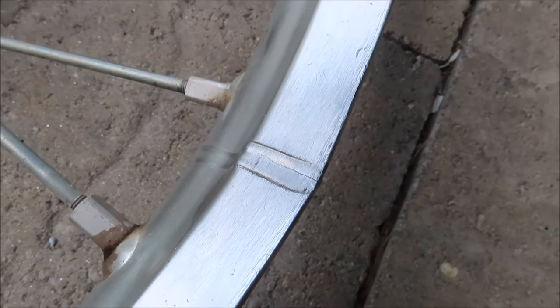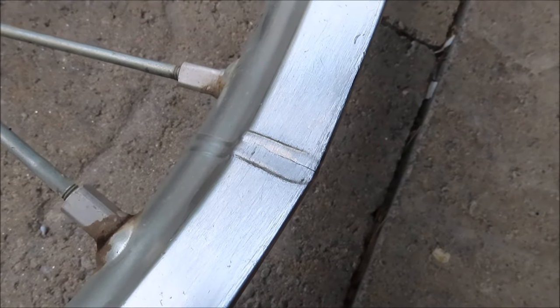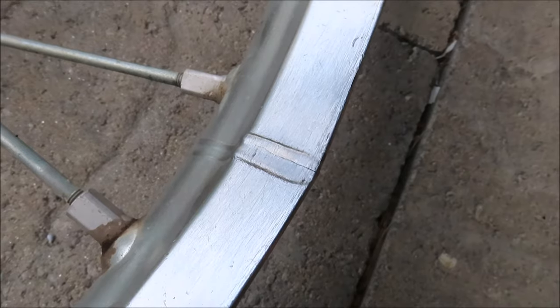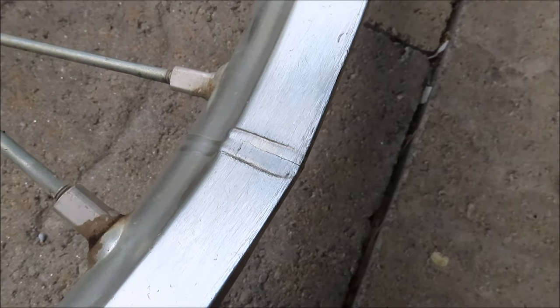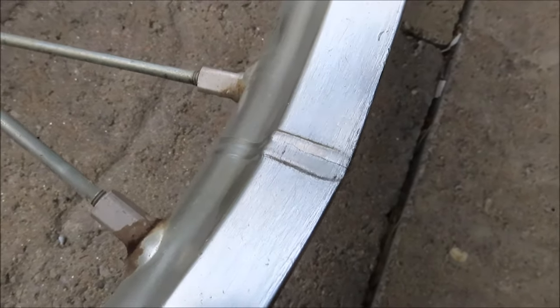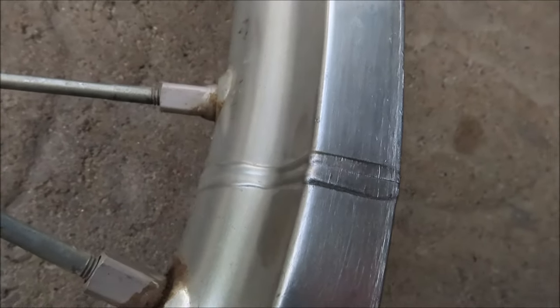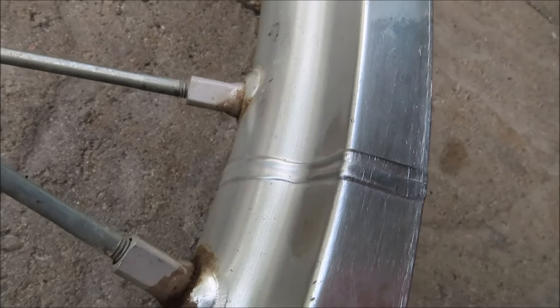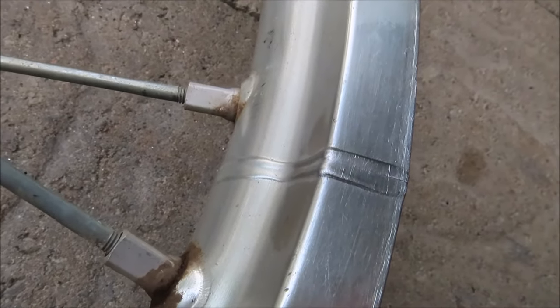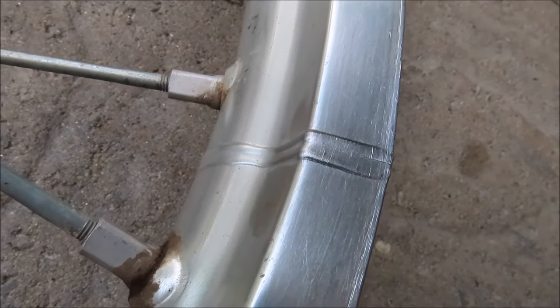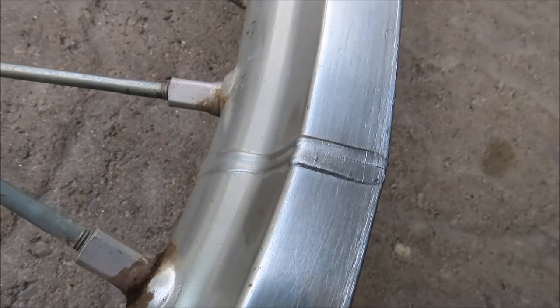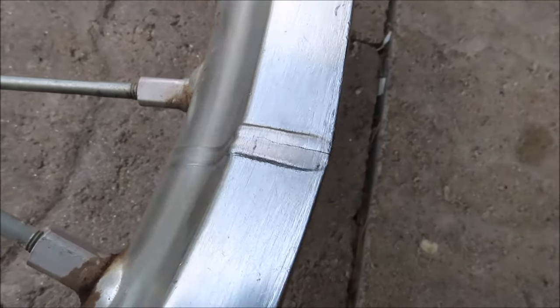No matter what I did, I couldn't get the temperature up enough to melt the welding rods, and this started to form, so I went ahead and stopped. As I was heating it up, it was bringing the crack together. As you can see, it formed this weird line all the way through. It's not a crack. I believe that since the wheel is under tension and heating it in that one spot, it started pulling it together.